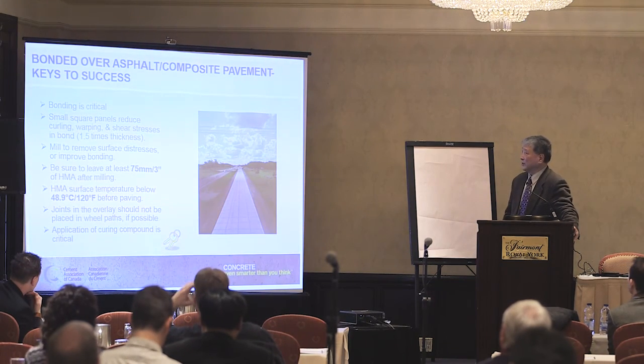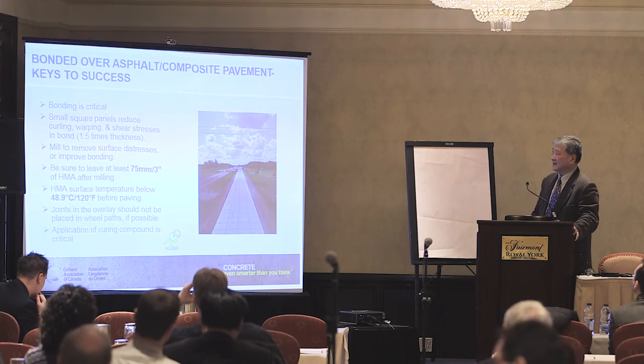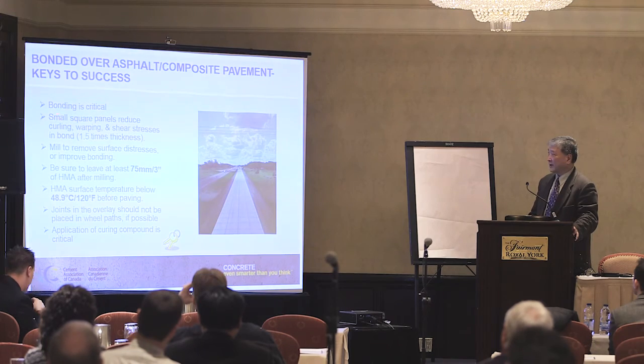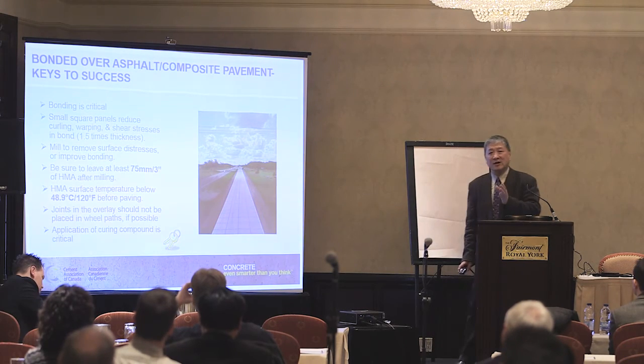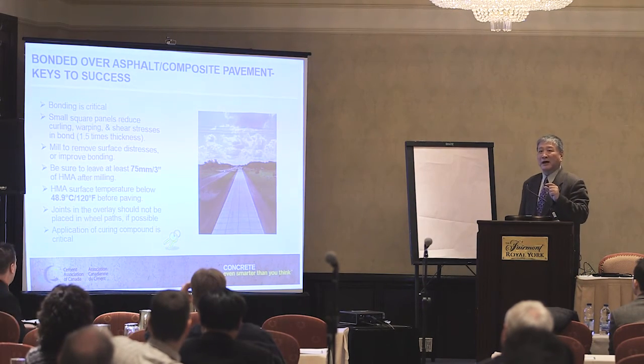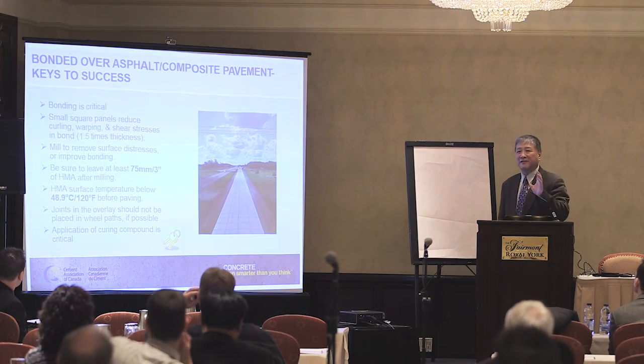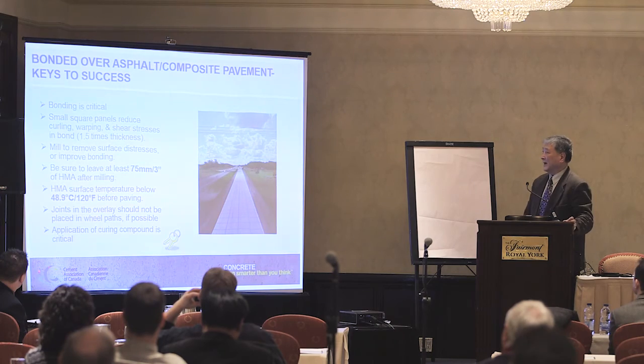For bonded concrete overlay on existing asphalt — a composite pavement — bonding is very critical. If bonding to existing asphalt, you don't need to match the joint, so you can dictate the saw-cut spacing; the rule of thumb is no more than 1.5 times the slab thickness as the maximum joint spacing. You must have a minimum 75 mm of sound asphalt underneath before applying the bonded concrete overlay.